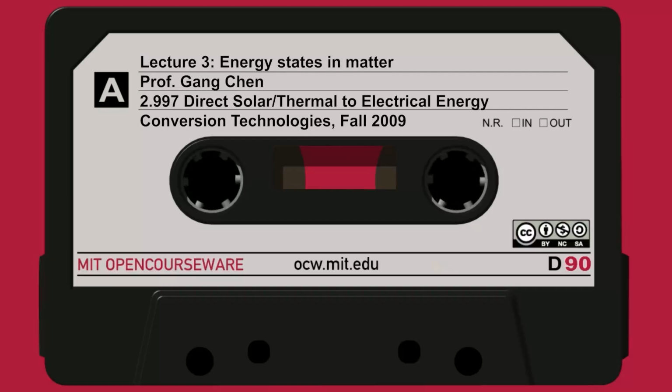If there are 2 atoms at a lattice point, then there are 3 acoustic branches, and then another N minus 1, so times 3, so there are 3 optical branches. If you have 3 atoms, you have 3 acoustic branches, then you have 6 optical branches, right? So the total is 3 times N, where N is how many atoms you have at every lattice point.